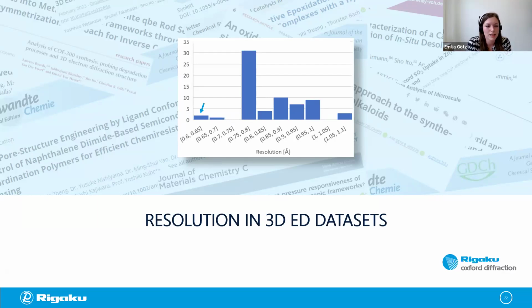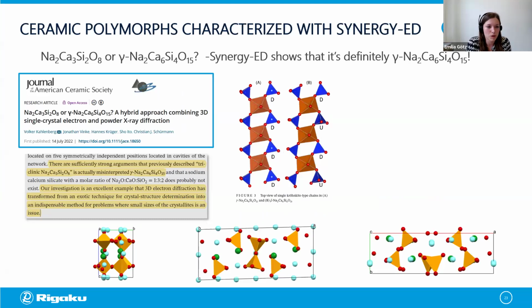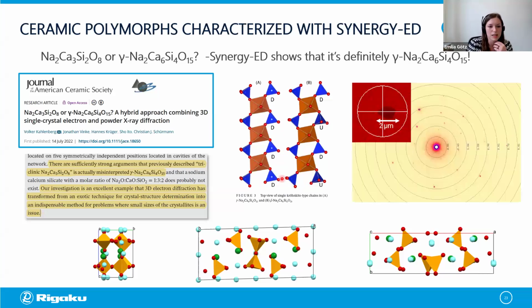And some had a really nice high resolution of around 0.6 angstrom, like this ceramic polymorph published by Kahlenberg et al. And here it could be shown with the help of 3D-ED that a triclinic sodium calcium silicate with a stoichiometry of 1 to 3 to 2 probably does not exist, but it is the gamma phase instead of the material, which differs from the beta phase by the orientation of every other silicon tetrahedra along this chain. And in this case, the crystal that was used for structure solution produced good diffraction signal up to 0.6 angstrom.